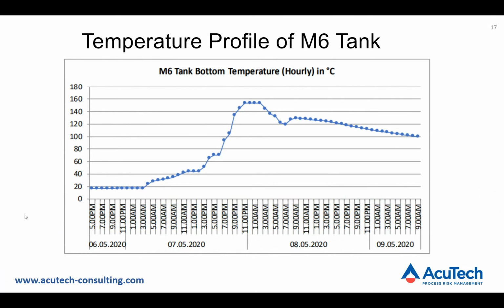This graph shows the temperature profile of the M6 tank. It is evident from this temperature graph that the temperature was by and large stable below 20 degrees centigrade until about 3 a.m. of 7th May. And then it started increasing thereafter. The rise in the temperature was sudden and occurred at fast rate, thereby pressurizing the tank.